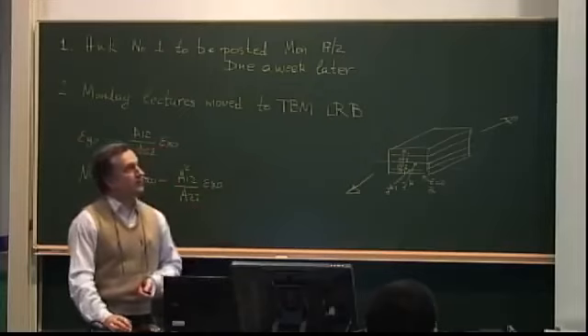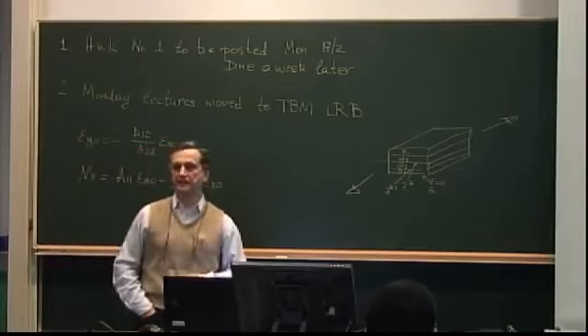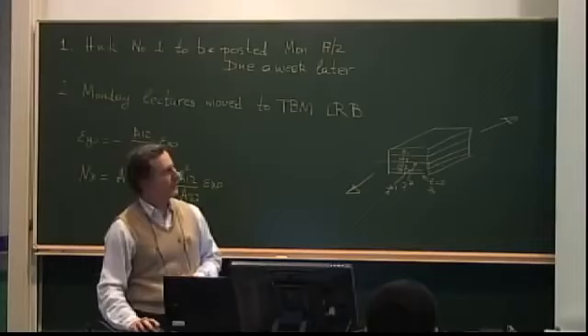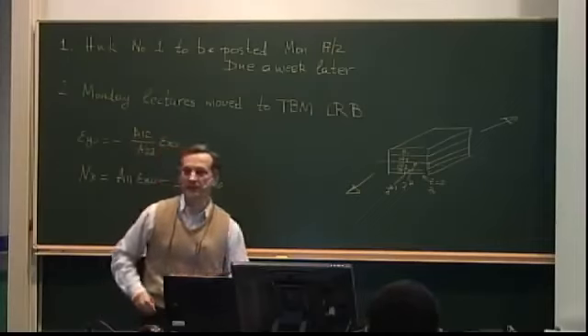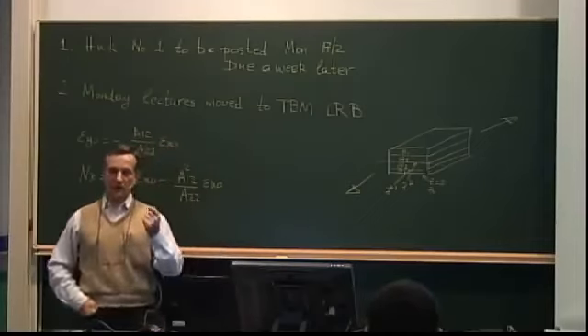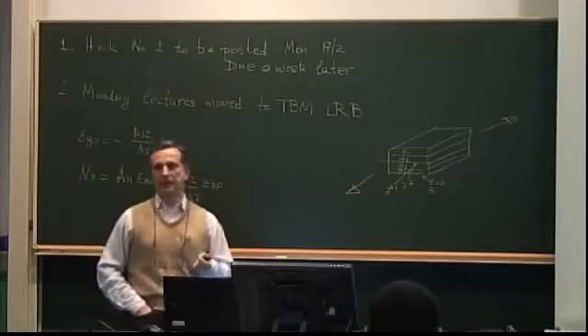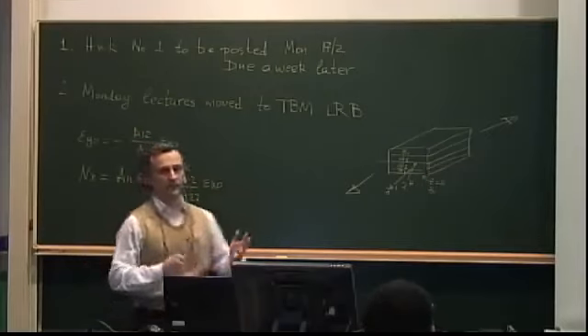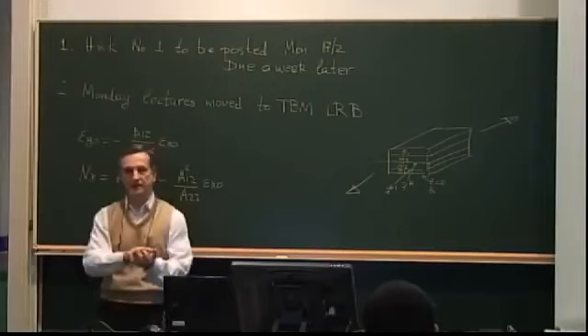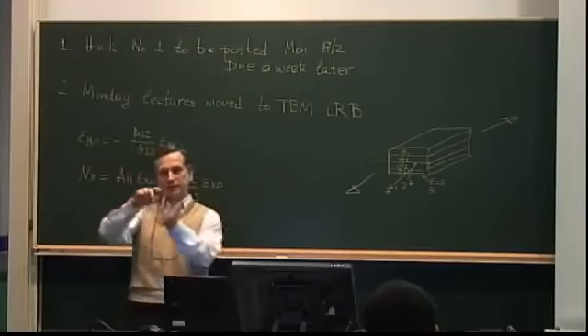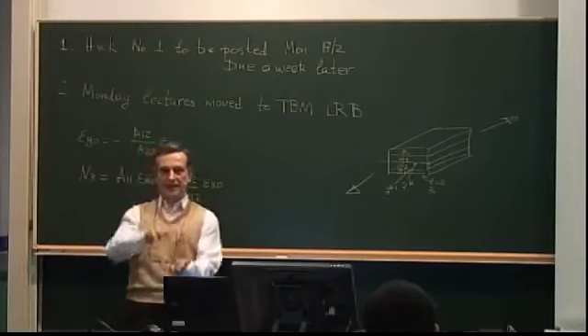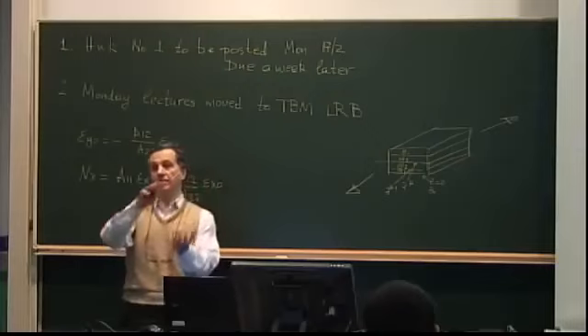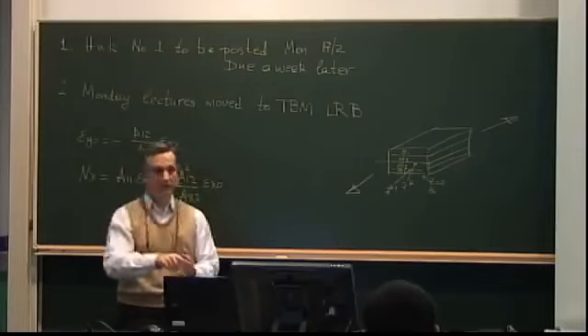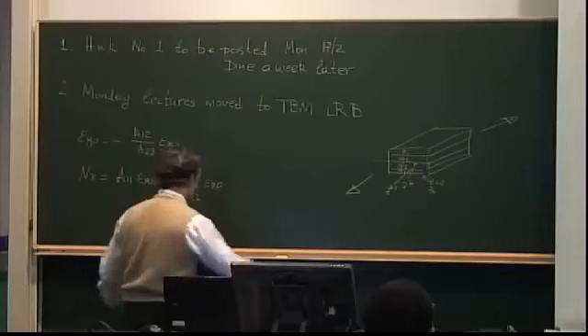Failure, as a rule, starts at the weakest link. It sort of makes sense, but if you compare it with what happens with stiffness, then it's actually quite insightful to think about it. If you're trying to calculate stiffness where you use a multiple set of materials, you will calculate the corresponding stiffness of each material and end up with the total stiffness as a weighted average of all the stiffnesses. For example, we said that for the A matrix,